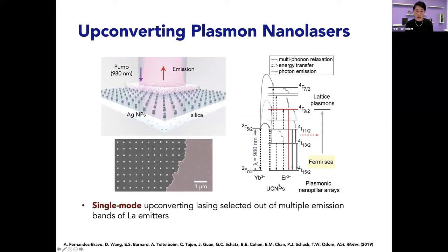And then this is the Jablonski diagram and the energy transfer that's expected, where you have a sensitizer, which is ytterbium, and an emitter, which is erbium. So we pump with longer wavelength light and we get out shorter wavelength. So this is the up conversion. And so the idea is, can you design a plasmon resonance that can overlap in energy with one of these transitions in these manifolds? So we'd like to be able to achieve single mode up converting lasing out of all of these different types of emission pathways.